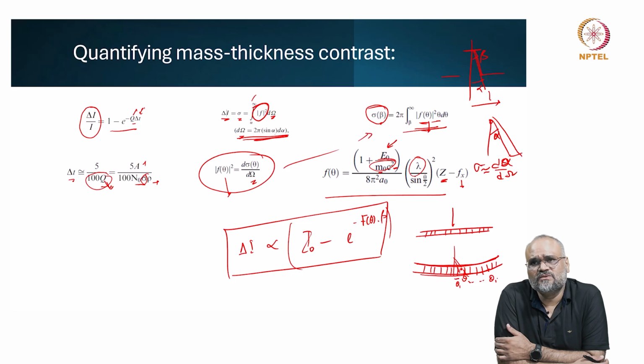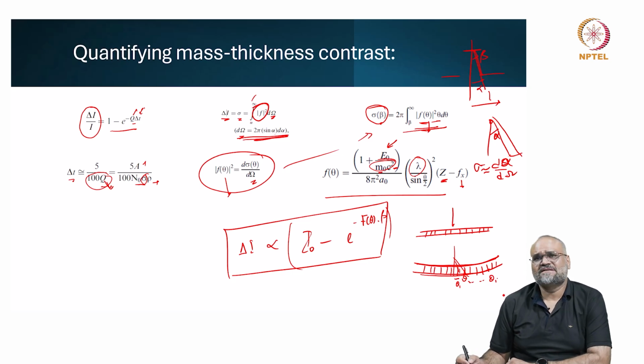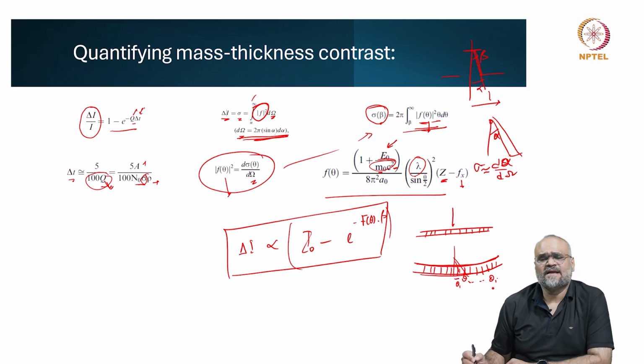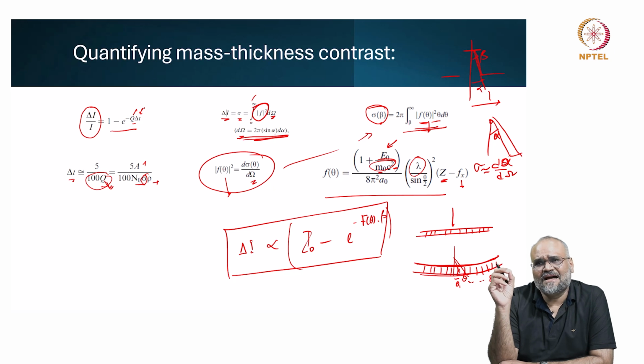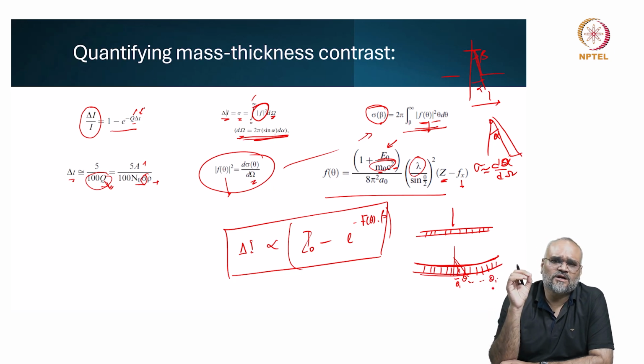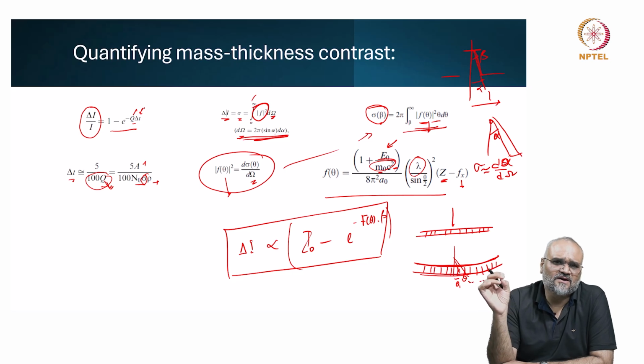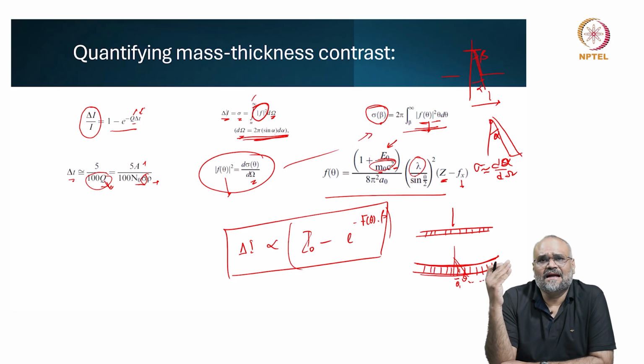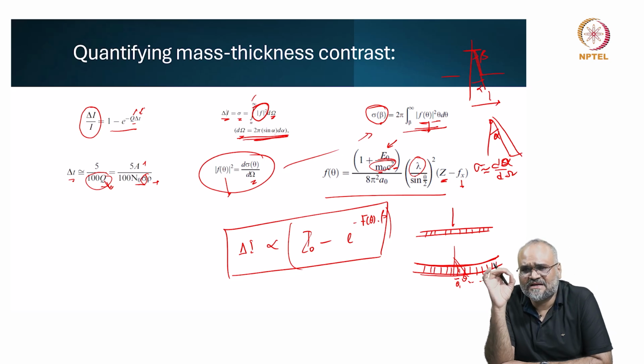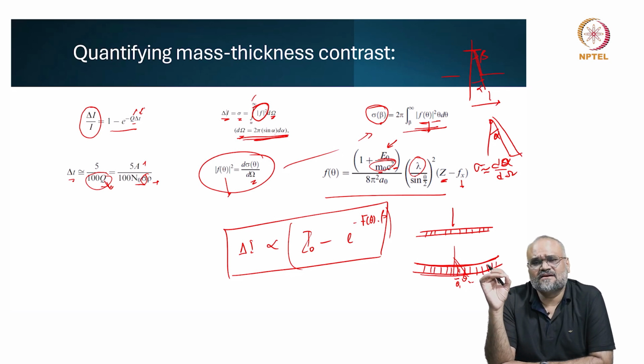And what you can also do is, once these forward scattered electrons are going along specific paths, I know at which angle they are going to be recorded at the back focal plane, and I can introduce something called as the objective aperture within the back focal plane, and by selecting a specific reflection, I can also record what is called as a dark field image.